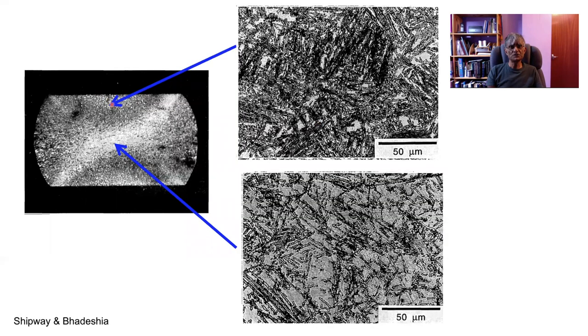So here is the region with very little plastic strain, and you can see we've got lots and lots of bainite. Here is the region with intense plastic deformation in the austenite prior to transformation, and we see very few plates of bainite. Okay. Now, this is a wonderful way of proving whether a transformation is displacive or reconstructive. It is only displacive transformations that are retarded in this manner, a process called mechanical stabilization, because when a reconstructive transformation happens, it actually destroys any defects that it encounters. So that gain in energy by destroying those defects actually accelerates the transformation, exactly like in recrystallization.